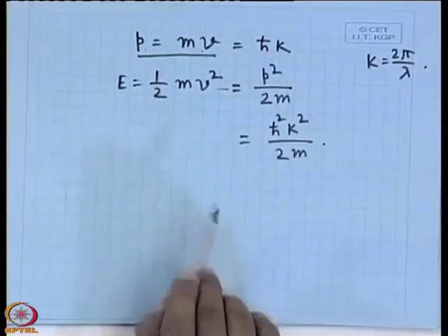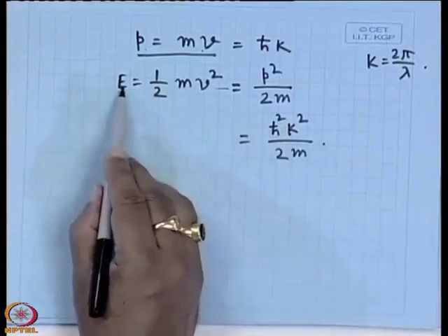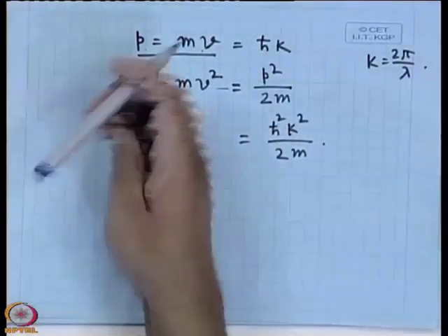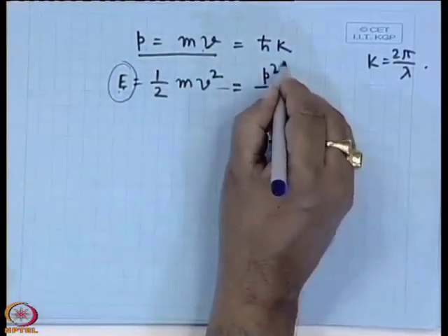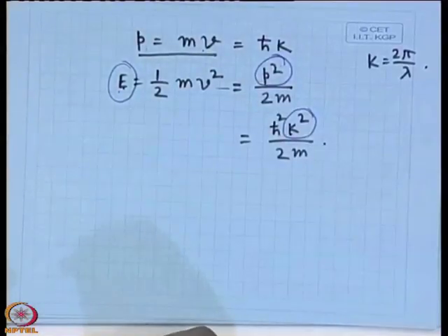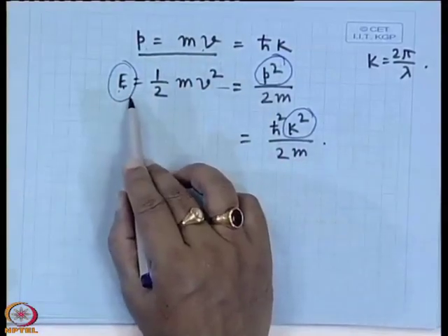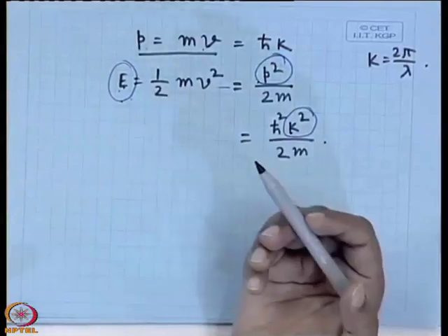So, that means E k diagram, here you see that E k diagram, this is E, this is k, is nothing but the E p diagram. Okay. So, if you plot E as a function of p, or if you plot E as a function of k, the nature will be same. It is parabolic in nature. But what is the implication of parabolic nature of a band gap? The implication is huge, because if you take this equation E equals h bar square k square by twice m, then